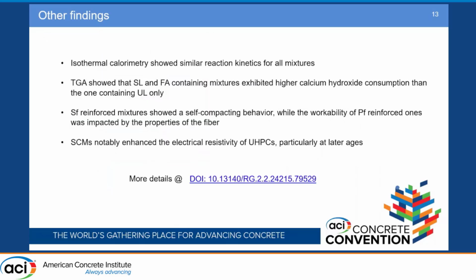We ran also a series of other tests evaluating even fresh properties of these mixtures. We saw that, for example, measuring the flow, the mixture with steel fibers really showed a self-consolidating behavior, while it was more challenging with the polyethylene fiber, even if consolidation helped a lot in that. But you can find more details in the link on the slide.